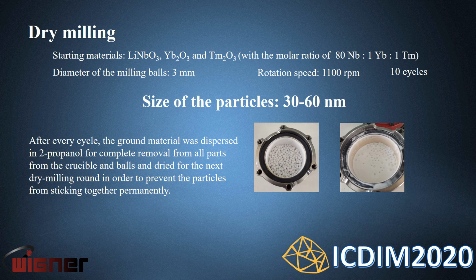The particle size we achieved was larger than we produced by the wet milling, but the dissolution of zirconium dioxide crucible, the balls and the sealing ring could be avoided.